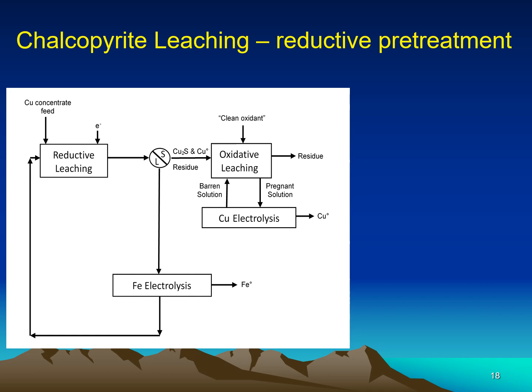The solid, which is now reduced to chalcocite and copper metal, is sent to the oxidative leaching stage, where the clean oxidant, the cupric ion, in the presence of acetonitrile, oxidizes the copper to cuprous ion. The pregnant solution is then sent to copper electrolysis.